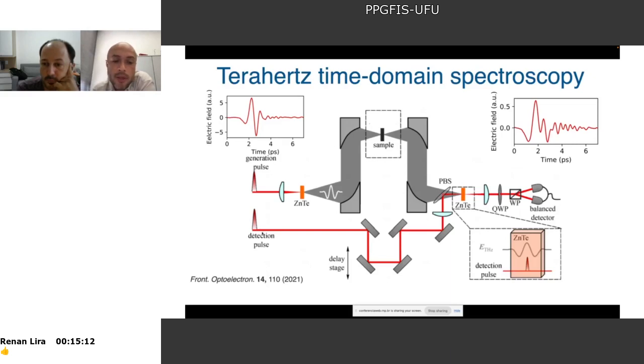And the second detection pulse follows a different path. The most important difference here is that we have a mechanical delay stage. So this part here can be adjusted, and like this you can change the delay between this terahertz pulse and the laser pulse arriving at the second crystal. And like this you can map the transmitted electric field, right?